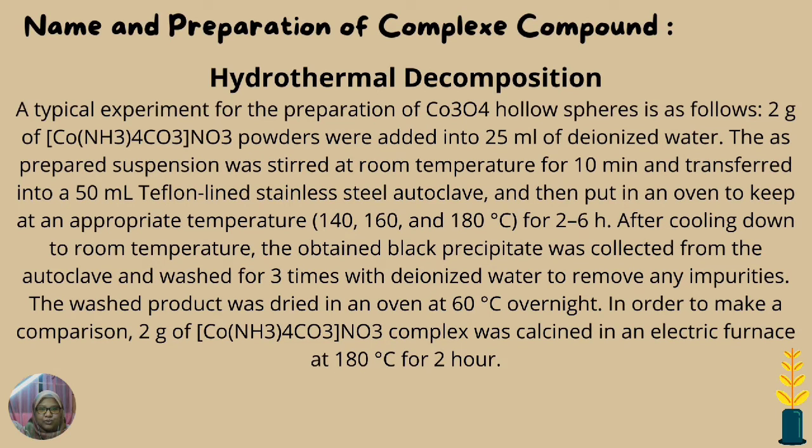So let me proceed to the preparation of the complex compound. The process is hydrothermal decomposition. A typical experiment for the preparation of the Co3O4 hollow sphere is as follows. First, 2 grams of [Co(NH3)4CO3]NO3 powder was added into 25 ml of deionized water.